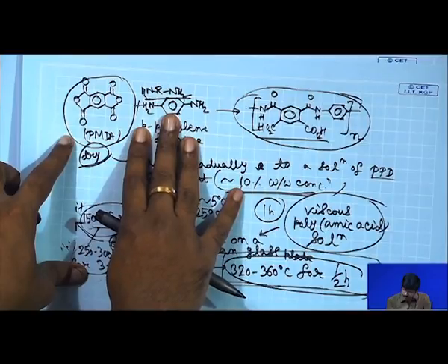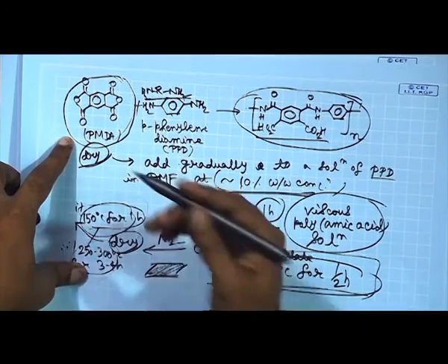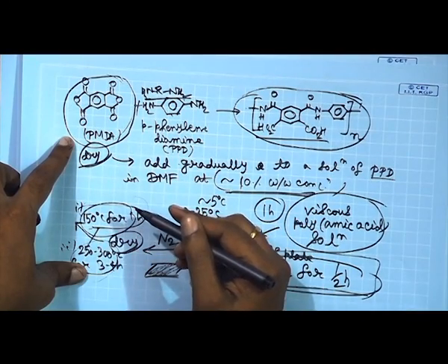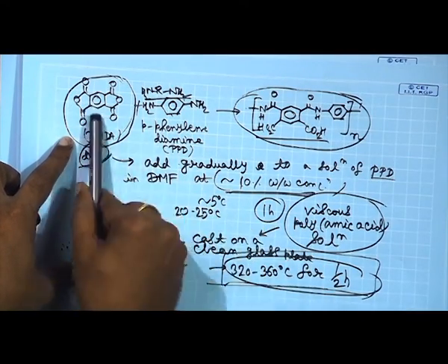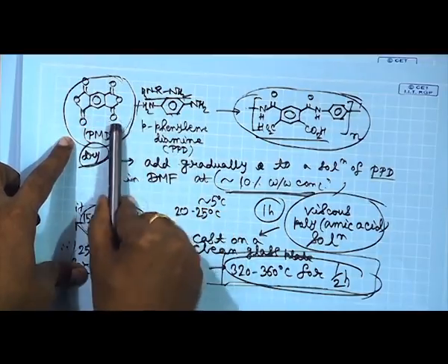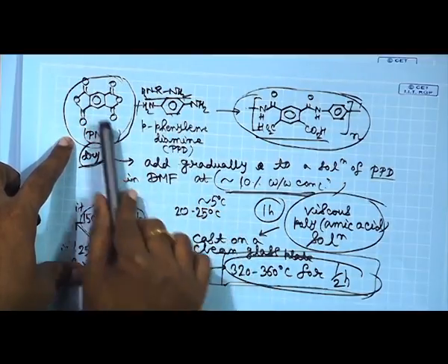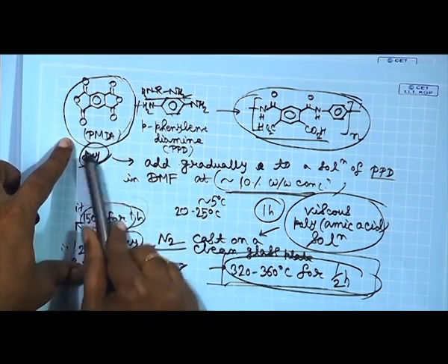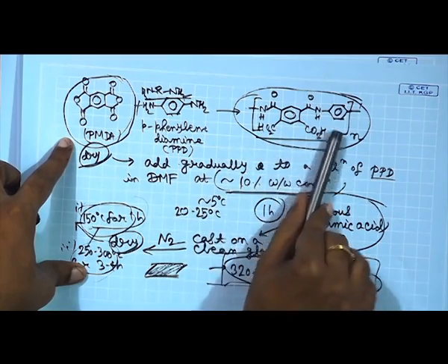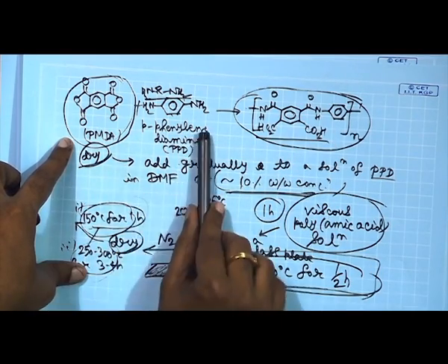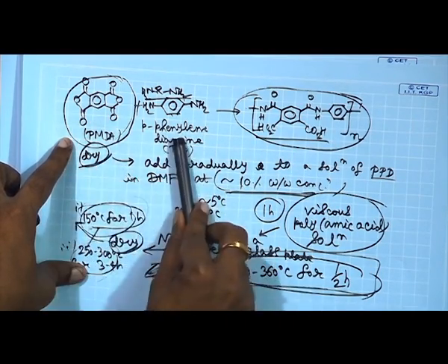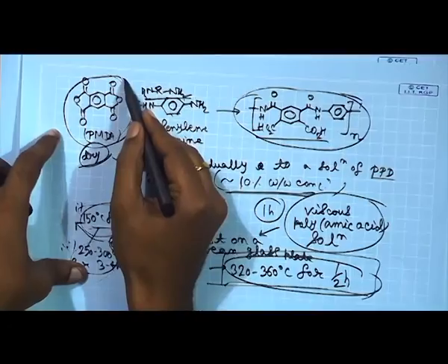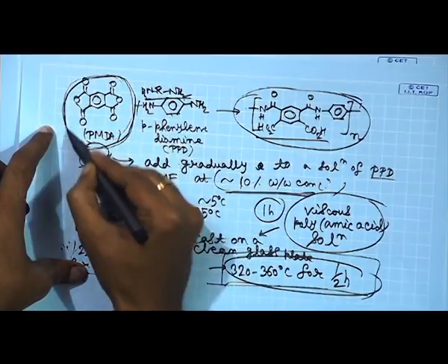Long before all the dianhydride has dissolved, you will get very high molecular weight polymer, and even before a stoichiometric balance has been achieved, you will start to get very high molecular weight polymer, even though finally when everything has dissolved you have a stoichiometric balance, because you have calculated the amounts in such a way. You do not need stoichiometric balance to get high molecular weight, a property of interfacial polymerization. It becomes in effect a solid liquid interfacial polymerization. Lastly, you want this to be dissolving very slowly.